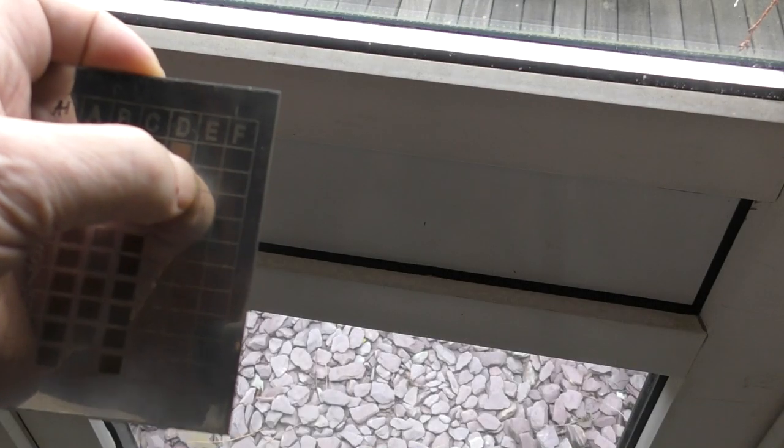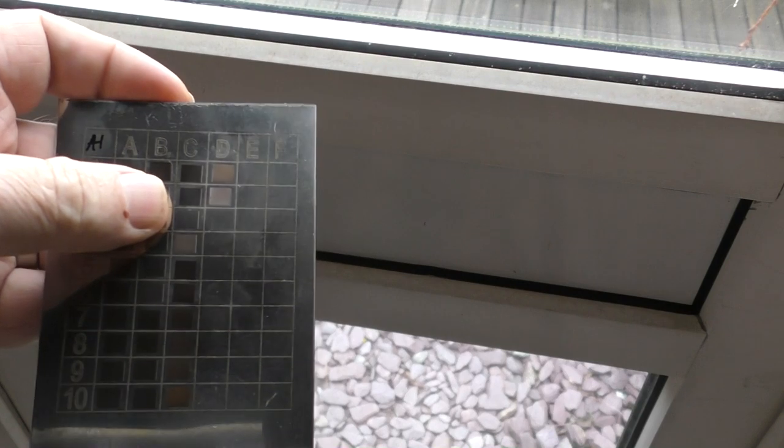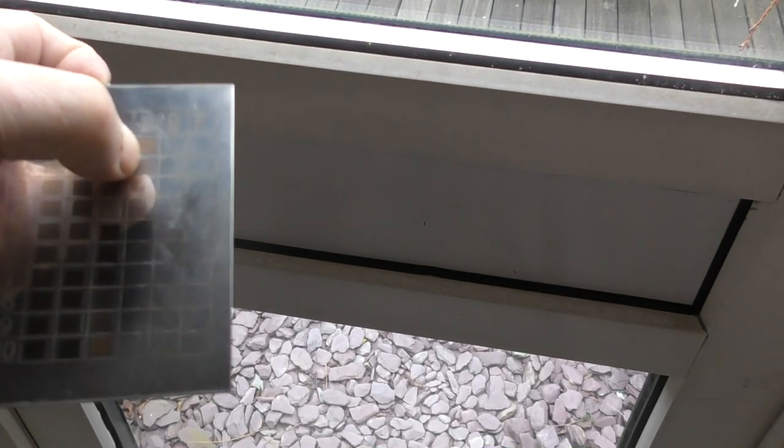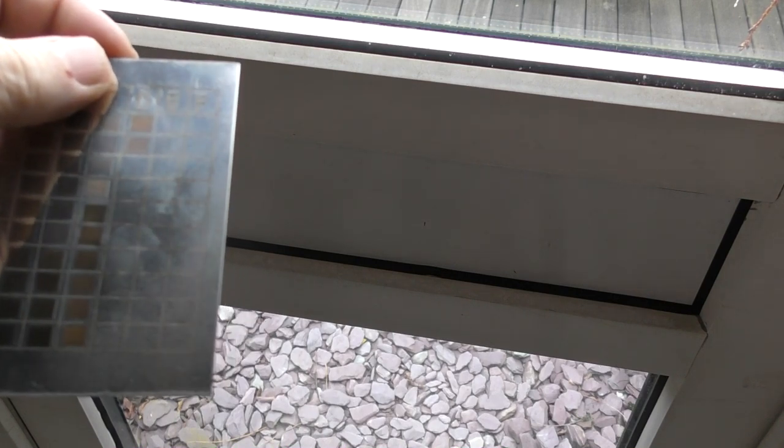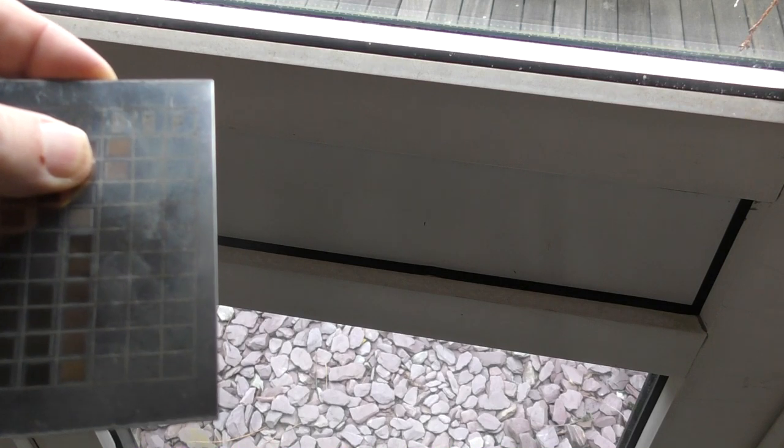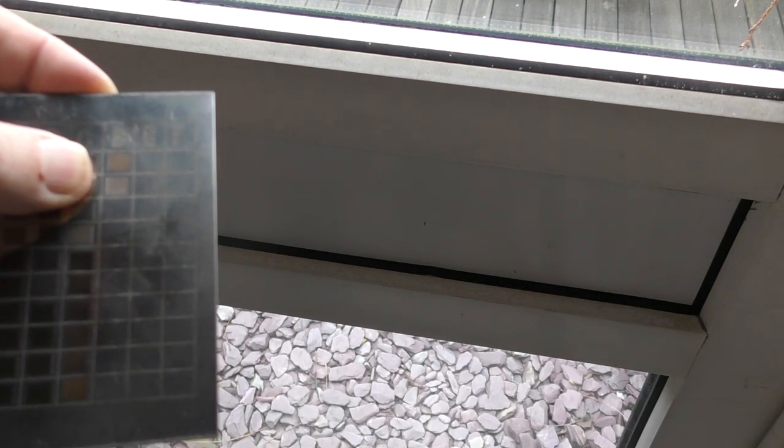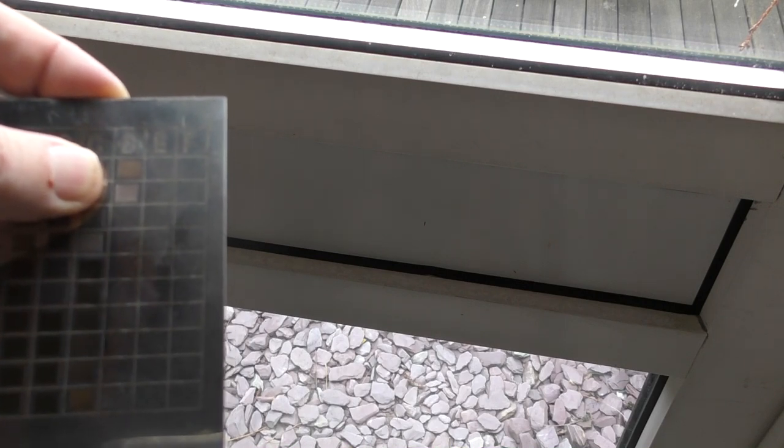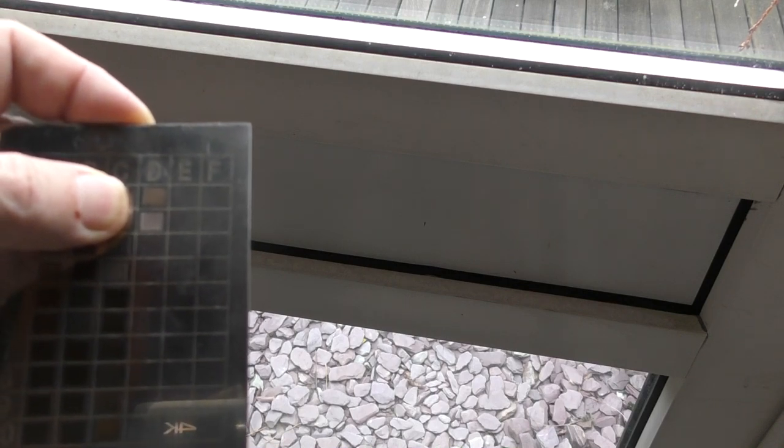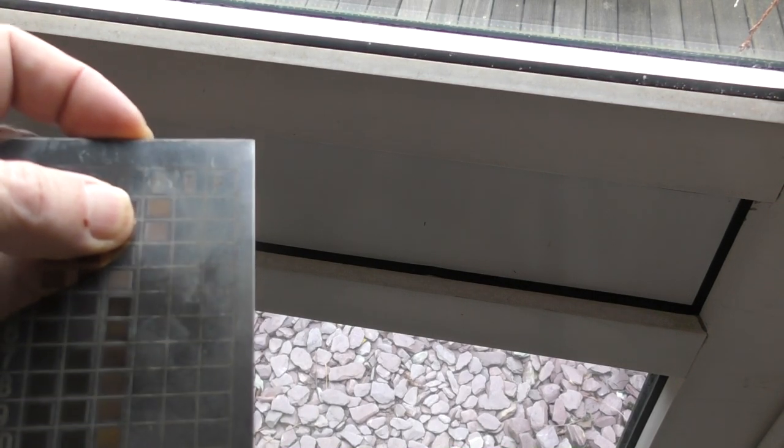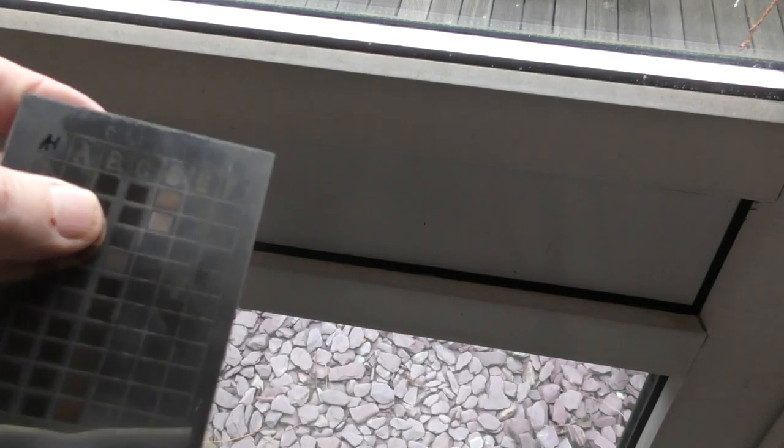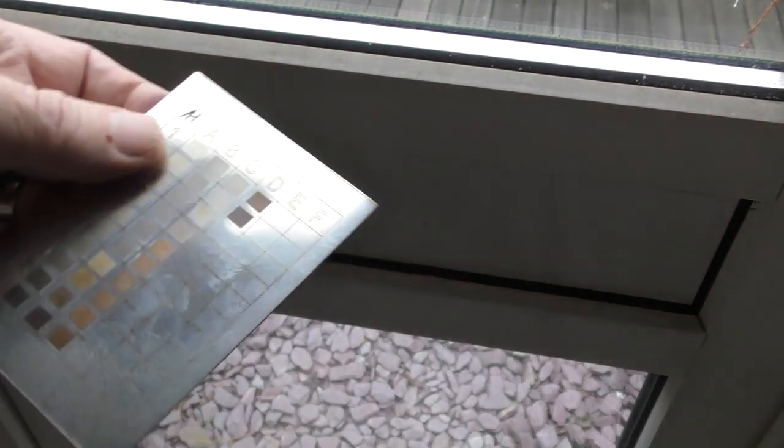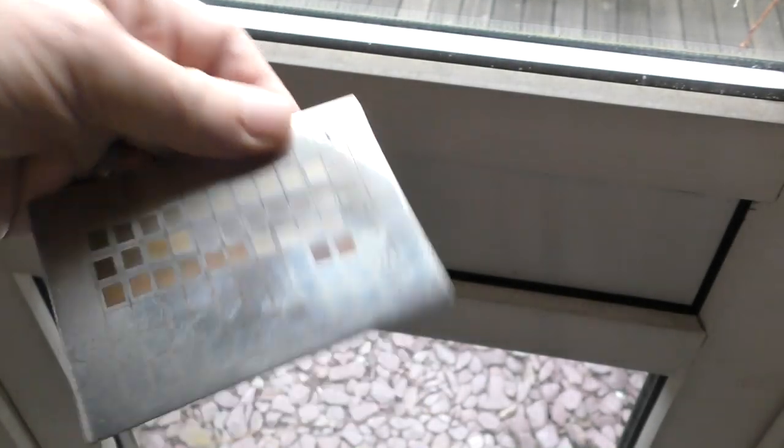As I feel it with my fingernail, both of these colors D1 and D2 have suffered surface damage. I can feel a real depth to that cut. Okay, it's not very much, it might only be about 0.2 or 0.3 of a millimeter, but there's definitely material missing from the surface. Now the only reason material can be missing from the surface is because we've evaporated it, and if we've evaporated it we must have put a very very high surface temperature into there. In doing so, I suspect that we've gone beyond melting the surface and just allowing it to reform. We may well have messed around with the chemistry of the material itself, and in which case that would account for why these particular colors are more solid, more pigment-like than the others. I mean the others are definitely they change very much with the light.